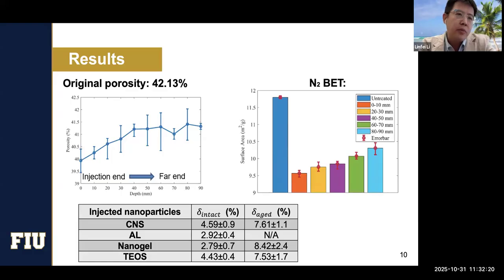We also did another BET test using nitrogen gas. Again, we will not be able to directly measure the filling, so we're using different types of indirect testing to prove the concept. We're measuring the surface area of the pores. As you can see, for untreated samples, just oil well cement samples, it has a relatively large pore surface area. But since the nanoparticles are injected, the pores are filled by the nanomaterials, so you have a relatively lower surface area of the pores.